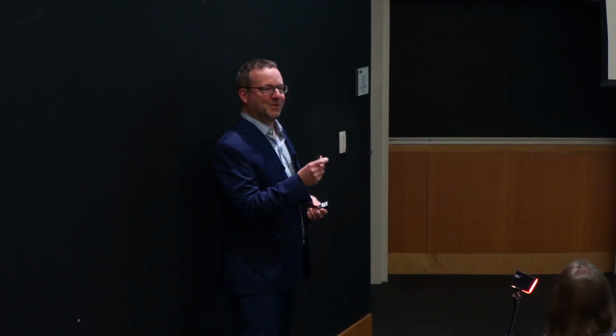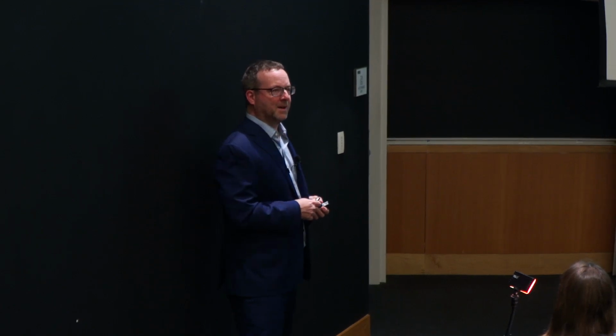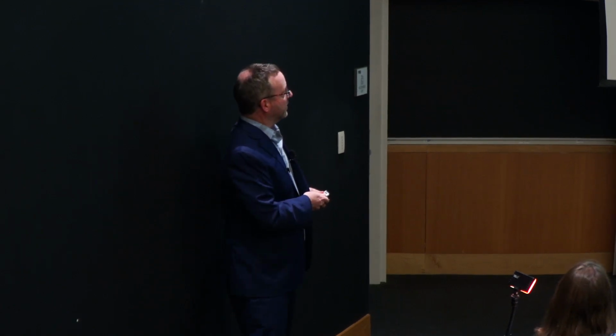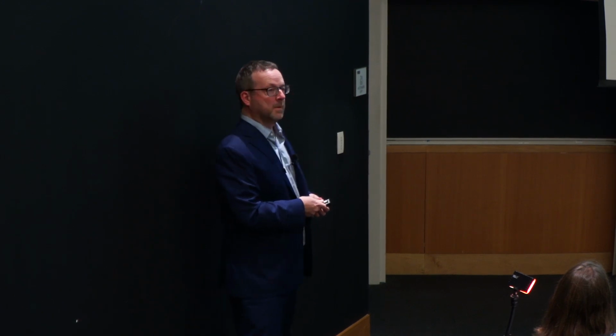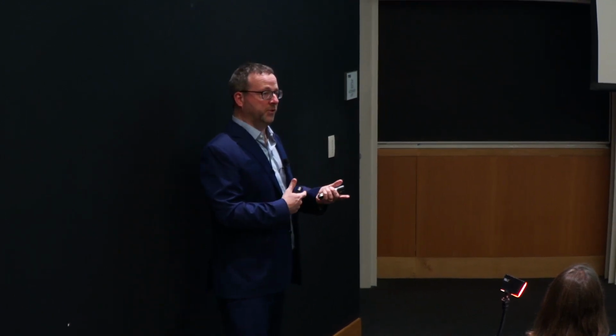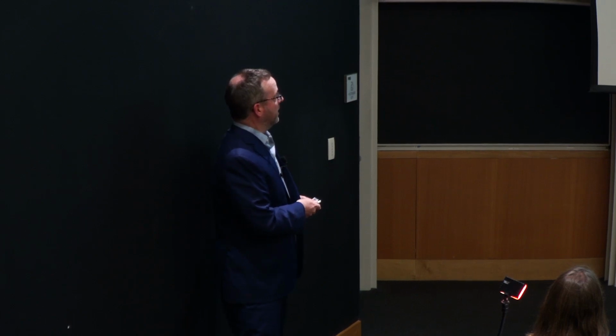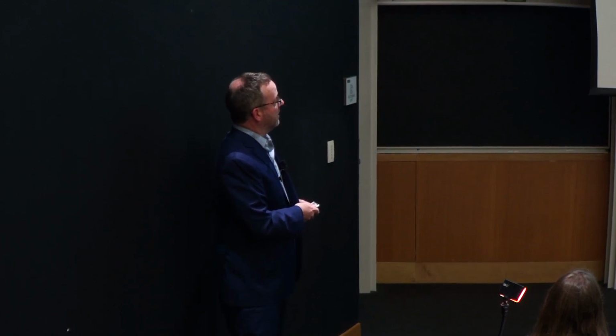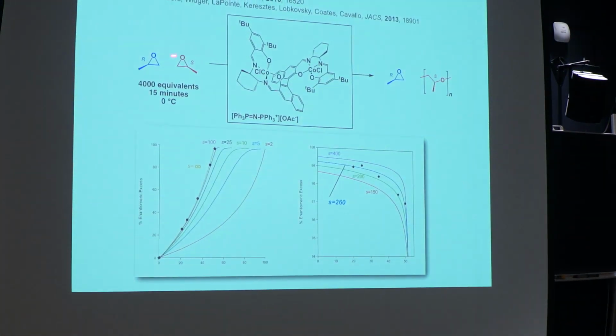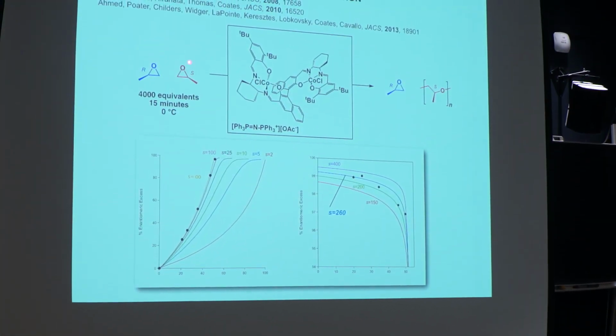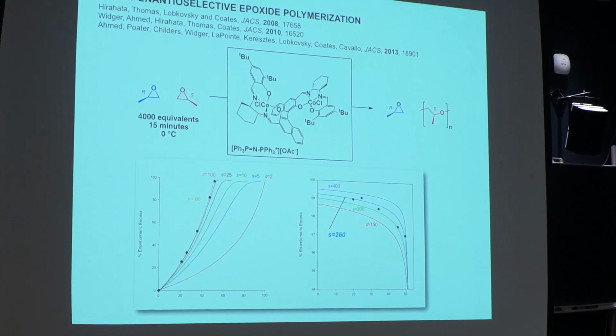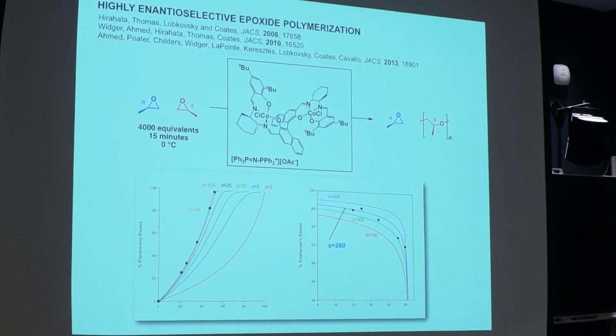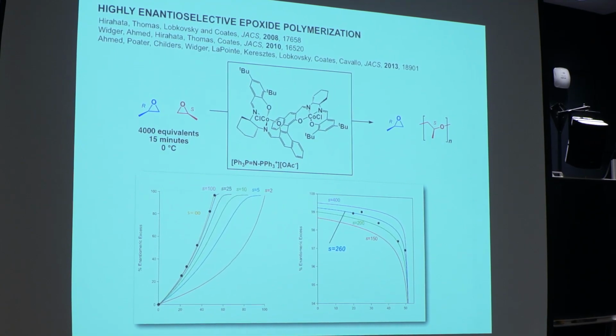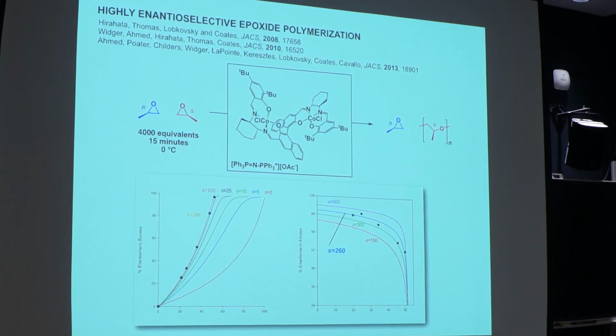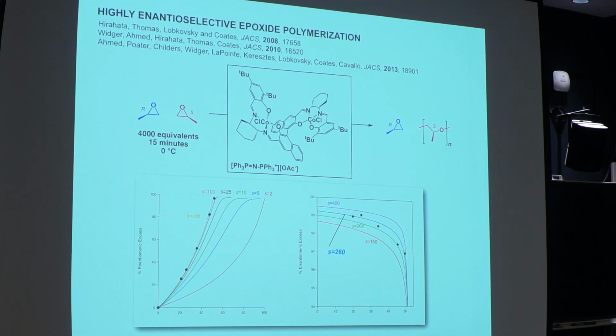So it's really hard to measure exactly the conversion of a volatile epoxide. And so the better way to do this is you actually look at the tacticity of this polymer. And if your catalyst is really good, you shouldn't have any stereo defects. And so here we can look at the EE of the product, and the best fit is about 260 to 1, meaning this catalyst will eat up 260 of the S enantiomer before it makes a stereo mistake and goes for the wrong enantiomer. Not quite as good as most enzymes, but still, you make a polymer product that's almost perfect in its tacticity.